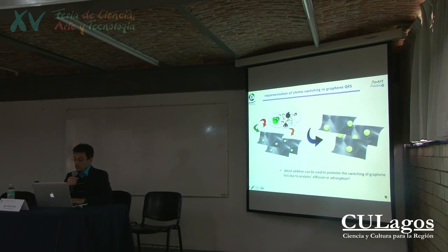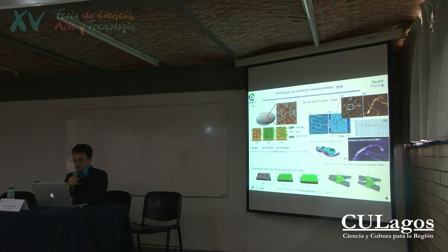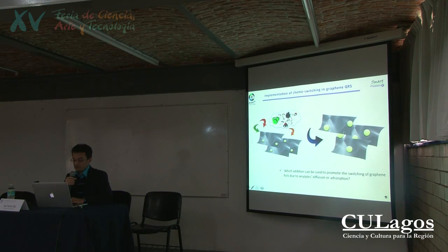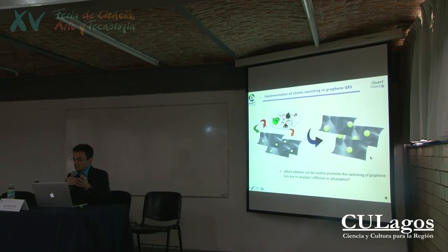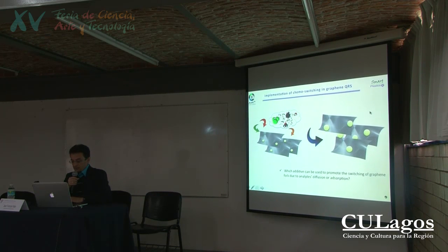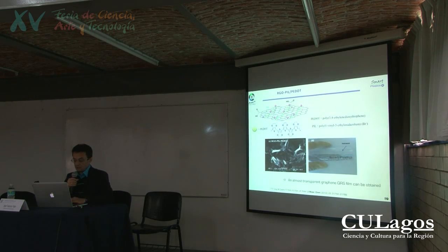When you are using foils, like graphene foils, the problem is slightly different from tubes, because the geometry, the morphology of the foil is completely different. So if you do nothing, you will pack the foils one onto another, and it will be very difficult to make them sensitive to organic molecules. So that's the reason why we have introduced some spacers, some molecules that will introduce spaces between the foils to allow the disconnection of the foils. If you have no disconnection, you have no electrical signal behind, so your system is not sensitive. So the use of the disconnectors is to introduce space, but also to introduce functionality.